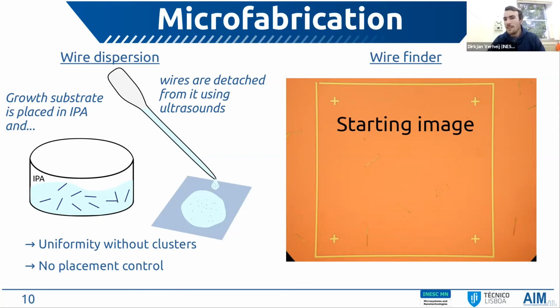However, that would lead... But wait, when you have SEM, your surface needs to be conductive? No, but I am able to see the wires in the SEM microscope without any contacts deposited. So in the SEM images I showed, we have the contacts, which makes it easy to find the wires, but even without contacts, I'm able to locate the wires and take pictures. However, this would increase the time it takes to perform this process with a huge amount.